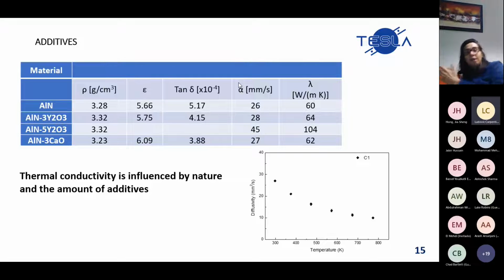Changing the additives will also change the properties of the material that we develop. Just with aluminum nitride, from the diffusivity we estimate by calculation the thermal conductivity of the material. As you can see, we are reaching 60 W/mK, changing the difference.